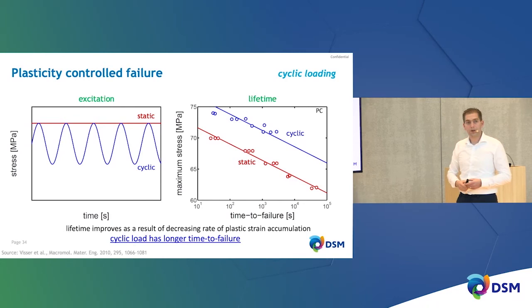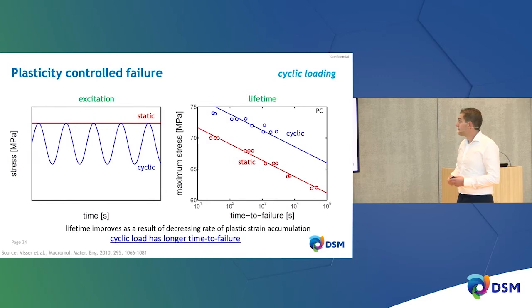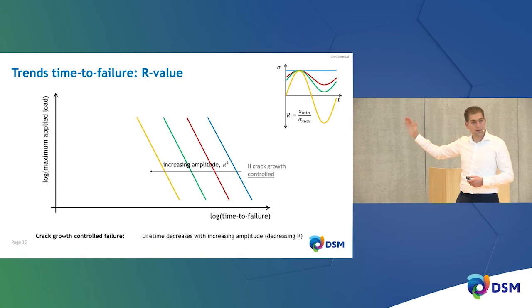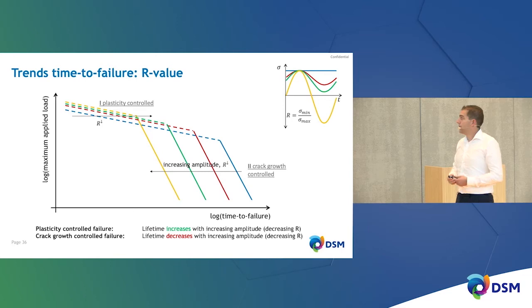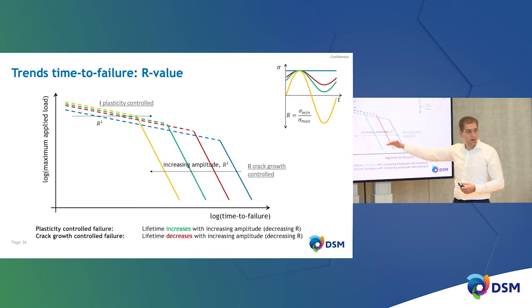Evidence for this is shown for polycarbonate: maximum stress plotted versus time to failure shows that for cyclic loads, lifetime indeed increases due to the decreasing rate of plastic strain accumulation. So a cyclic load results in longer time to failure. This is counterintuitive because for crack-growth controlled failure, lifetime significantly decreases with increasing amplitude, whereas for plasticity-controlled failure, decreasing mean stress actually causes an increase in lifetime.